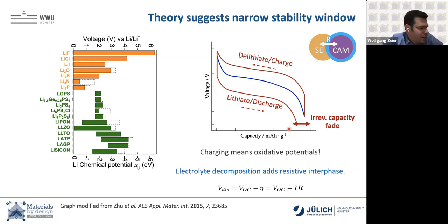Well, Yifei Mo, he's in Maryland, it's now 6 years ago, he put out this really cool paper showing the potential windows of solid electrolytes that people are using. And just to walk you through this graph, anything that is at 0 means it's stable against lithium, for instance. All of the lithium binaries, they're thermodynamically stable against lithium by definition, of course. But the materials, for instance, the argyrodites that we're working with, oh my goodness, they have very narrow chemical stability windows. They shouldn't even be working in these solid-state batteries, but they do.